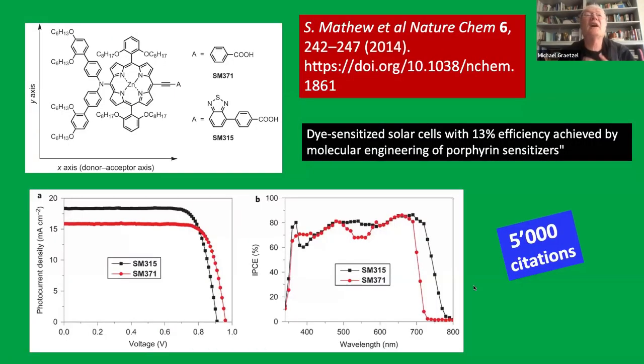And so this has given rise also to optimized structures. And here we have the first dye-sensitized solar cell that achieved 13%, published in 2014. And that paper also is a very highly cited paper, because you can see in the black dots here that a single sensitizer can capture the whole visible range, and over 80% of the incident photons, the photons that hit the cell, are converted to electric current.